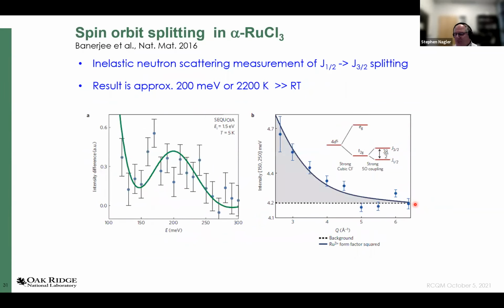Now, alpha ruthenium trichloride has ruthenium 3+. Roughly speaking, this sort of scenario holds, and there is a spin orbit level. So I show here a neutron scattering measurement of that spin orbit level, which can also be measured in other ways. It's not an easy measurement since you have to go to fairly large momentum in order to do it. And as Peng Chang and Jeff and others know, that makes it difficult to see the magnetic signal, but it can be seen, and it turns out to be about 200 meV. So that's roughly speaking thermal energies of a couple of thousand Kelvin.